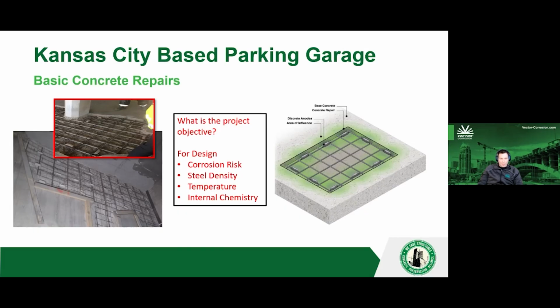So the first example I want to talk about is a Kansas City-based parking garage. It's cast in place. It was experiencing concrete deterioration that was corrosion driven. And we needed to determine the best way to target the underlying cause and ensure the repairs don't fail early. Ultimately, we're trying to put the owner's money to the most effective use. You can see in the pictures on the left, you can have the anodes installed at the perimeter or on a grid to prevent the halo effect as necessary. So the halo effect is going to work in three dimensions, depending on where the exposure of chloride is and your steel layout. So you may need to put them on a grid, and in some cases, on the perimeter may work just fine as well.